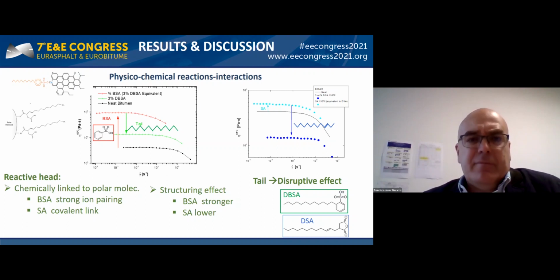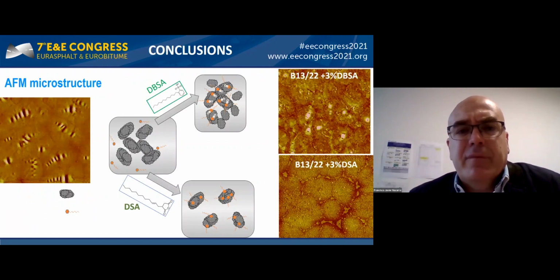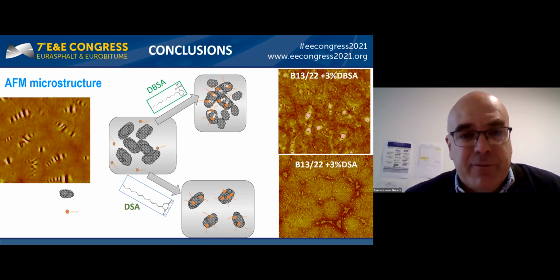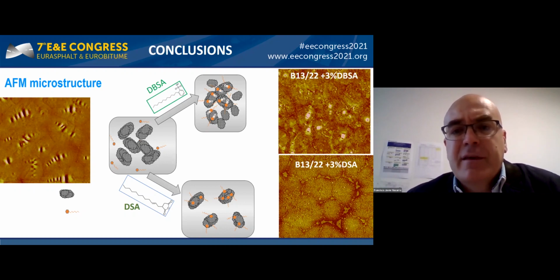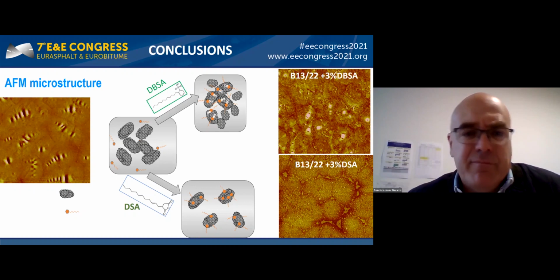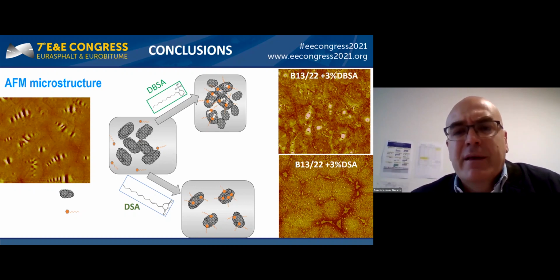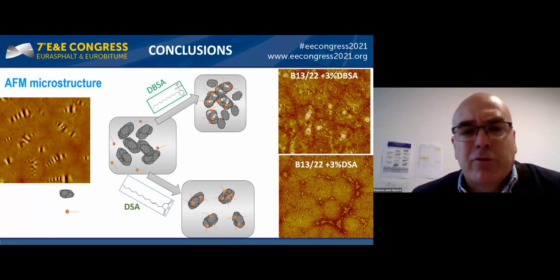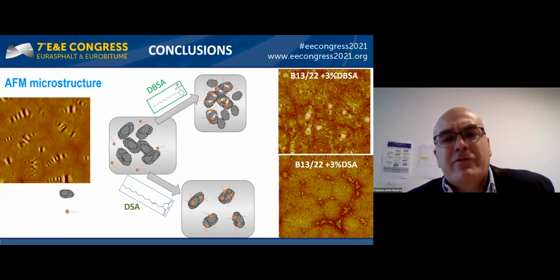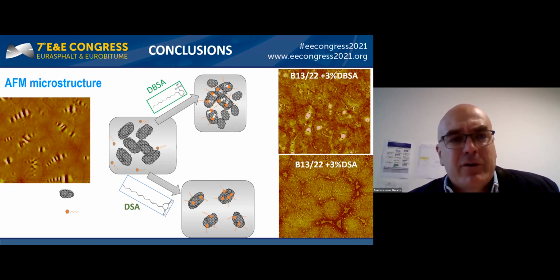Finally, by atomic force observation, these effects can be corroborated. In the case of succinic anhydride, the disruptive effect of the aliphatic tail is dominant because the covalent link hardly contributes to the asphaltene aggregation. And by contrast, in the benzene sulfonic acid, the disruptive effect of the aliphatic chain is clearly exceeded by the structuring effect of the polar head. Then the ionic pair formed by acid-base interaction favors the association of asphaltenes into larger structures, leading to the formation of new structures, enhancing the rheological behavior.